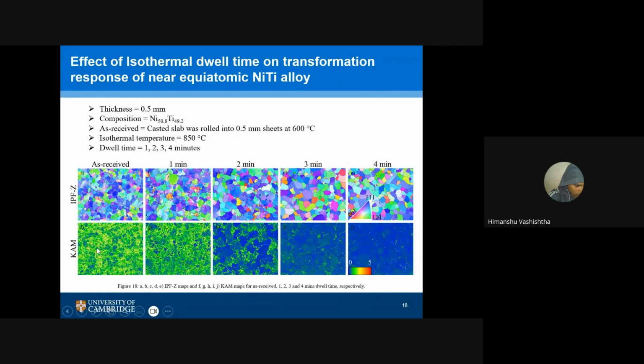Blue is the lowest value, and green or yellowish is on the higher side. You can see this scale from 0 to 5. So we are in the yellow and green region, on the higher side. When I heated it for one minute, it lowered, not significantly, but at 2 minutes it shows a drastic change, a significant recovery, and then at 3 and 4 minutes. With increase in time, we have not shown results beyond 4 minutes because after that it's almost recovered, meaning all the dislocations have almost recovered.